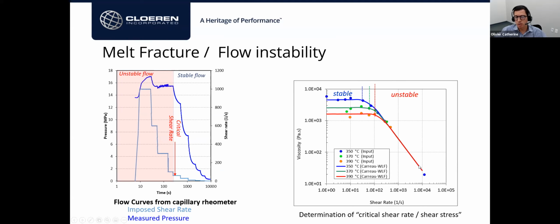If you calculate the pseudoplastic index there, it will be 0, which means that it doesn't have any physical meaning for the material. It's only slipping there. It's a very unstable flow. But we are able to detect with both graphs here, we can see the transition from unstable flow to stable flow. In literature, that's called a critical value of shear rate or shear stress, depending on how you see things here.